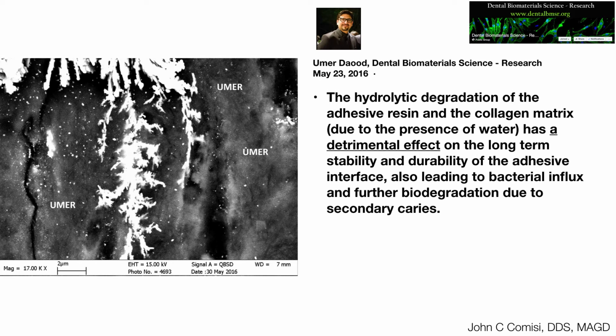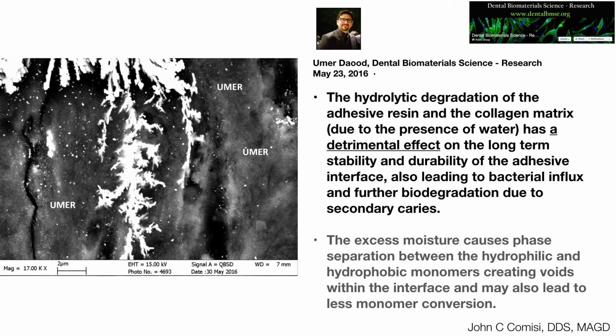He finally states that the hydrolytic degradation of the adhesive resin and the collagen matrix due to the presence of water has a detrimental effect on the long-term stability and durability of the adhesive interface, leading to an influx of bacteria and further biodegradation caused by secondary caries. This excess moisture causes phase separation between the hydrophilic and hydrophobic monomers, creating voids within the interface, and may also lead to less monomer conversion.